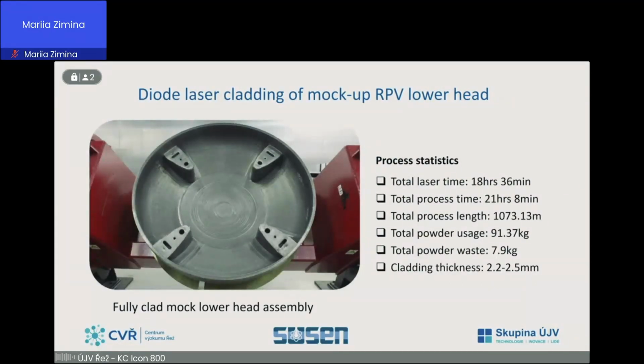And this is the last slide, which shows that all internal surfaces of the mock-up lower head assembly have been successfully clad with total laser time 18 hours, total process time 21 hours, total powder usage 91 kilograms. The total powder usage was roughly 3 or 4 times less than one would see for a conventionally clad component using submerged arc welding. I thank you for your attention.